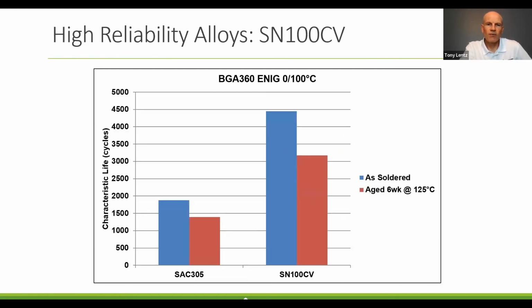Here's similar data for a BGA 360 that was cycled at a different temperature range, 0 to 100 C. The blue bar is as soldered and the red bar was aged 6 weeks at 125 C. Again, the characteristic life for SAC305 drops off as it does a little for SN100CV, but the overall life for SN100CV was much better than SAC305 in this test.